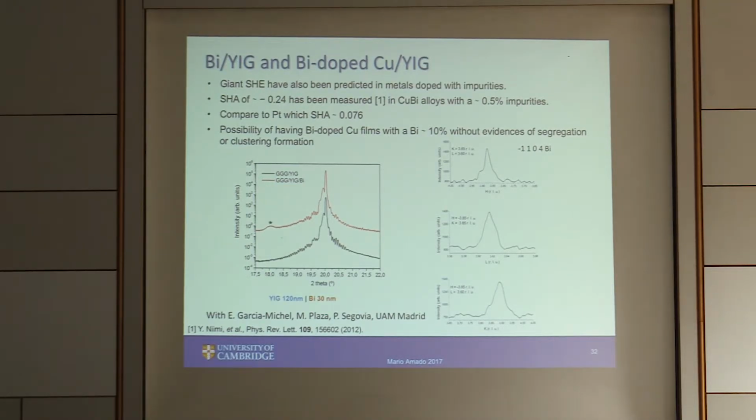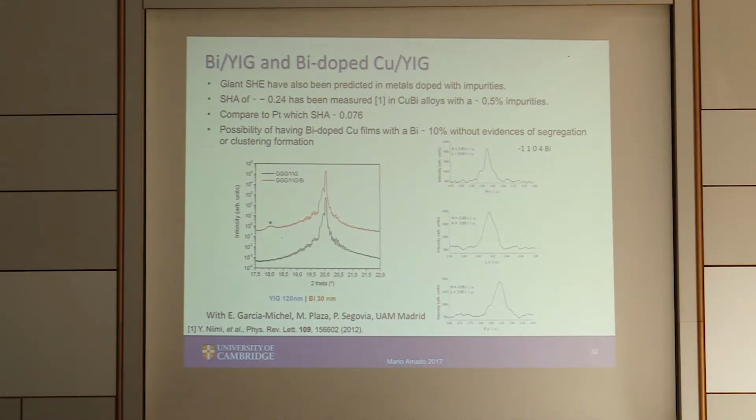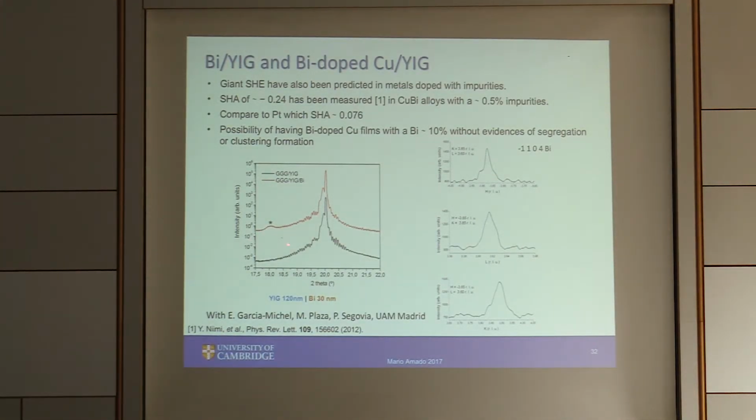It was pretty challenging just depositing in situ monolayers of bismuth on YIG. What we have observed is that it's possible to grow bismuth on YIG, even though the crystallinities and the unit cells are extraordinarily different, which is oriented out on the z-axis, out of plane. In plane, we probably have a polycrystalline film; out of plane, what we have is a pretty decent oriented film. So we can grow high-quality bismuth on the YIG.